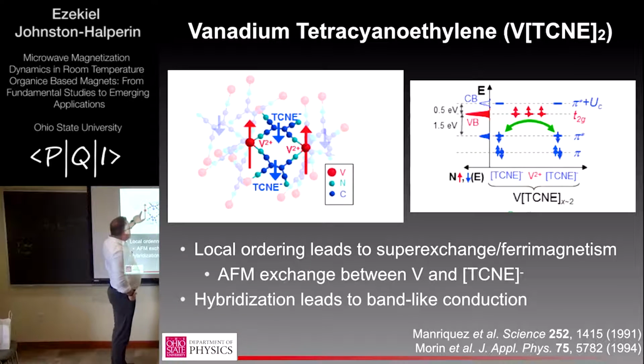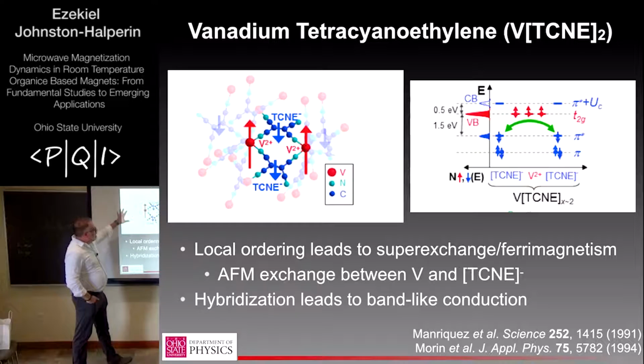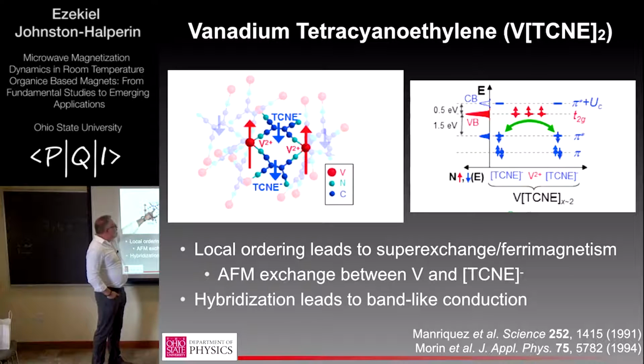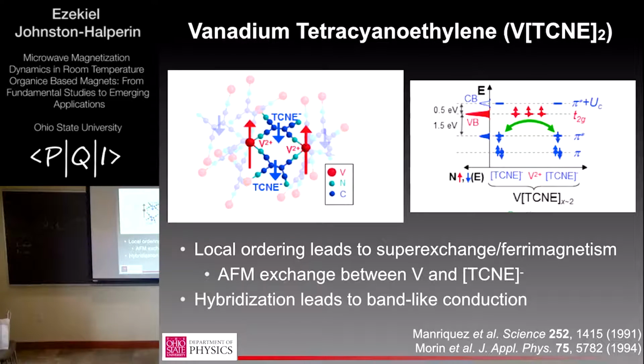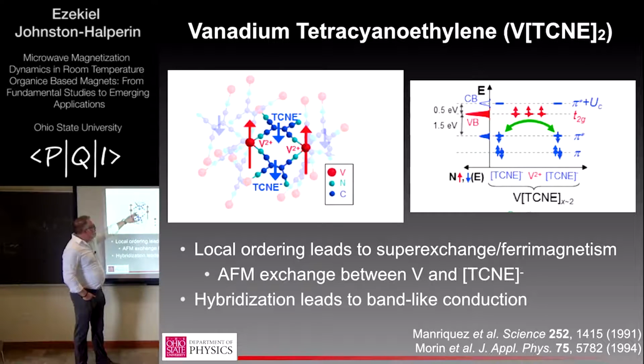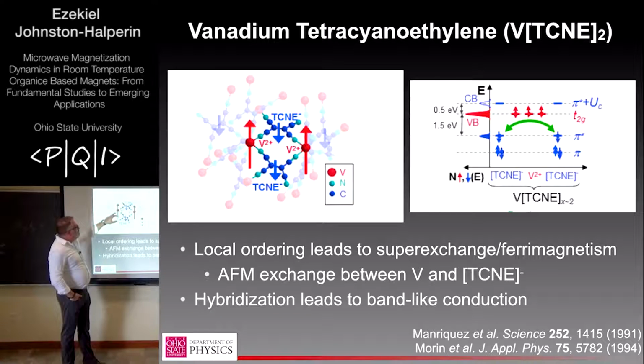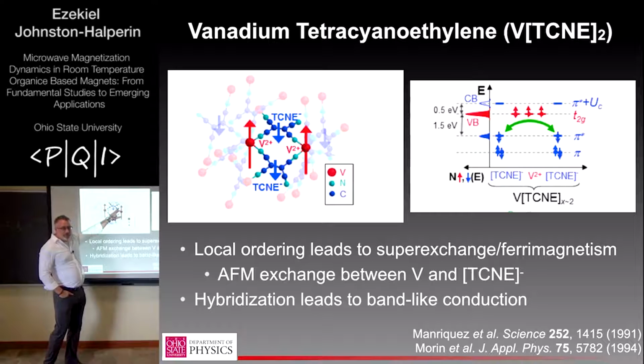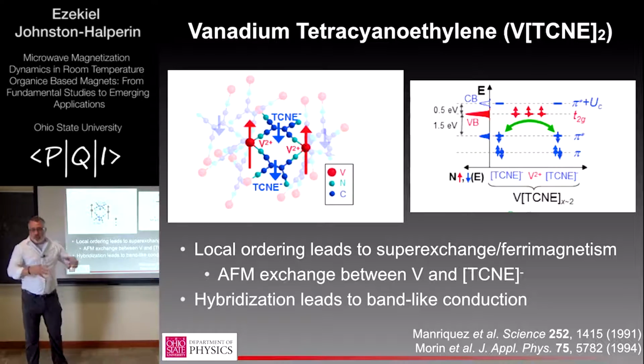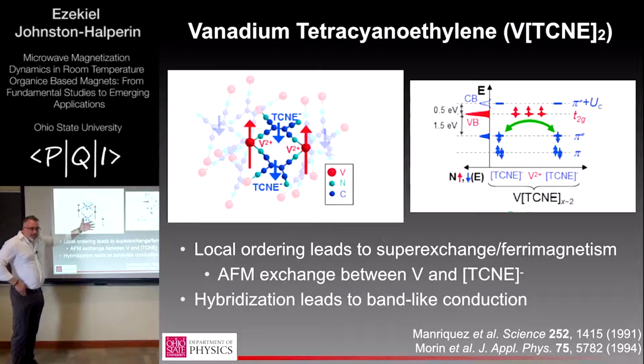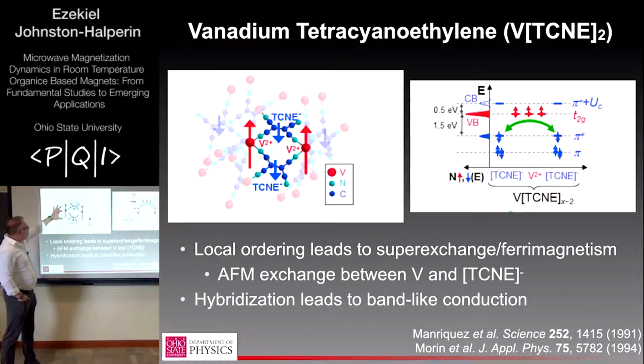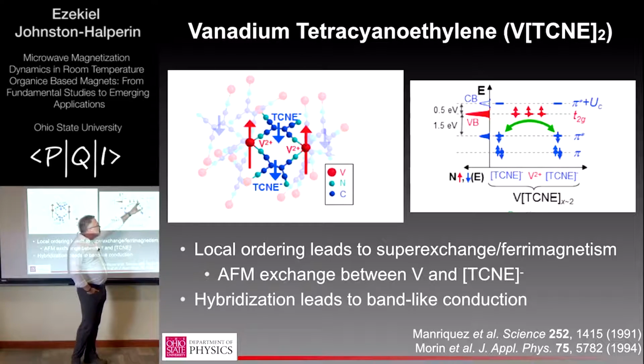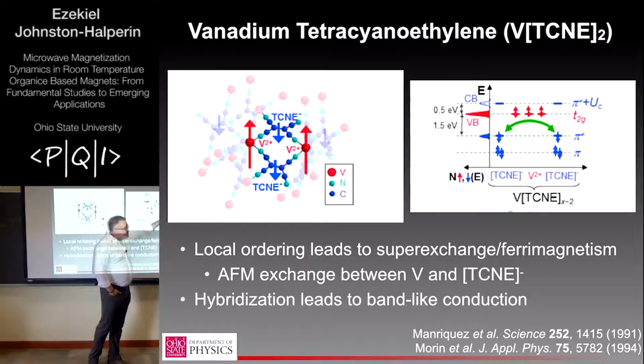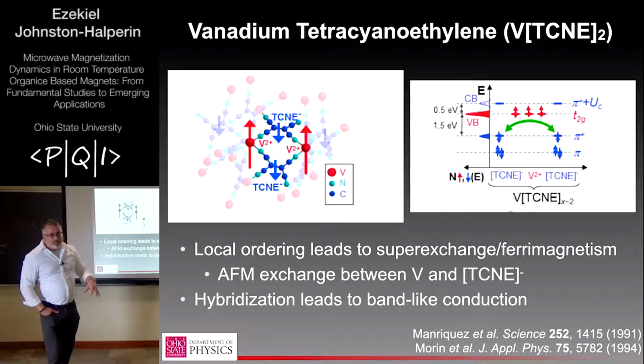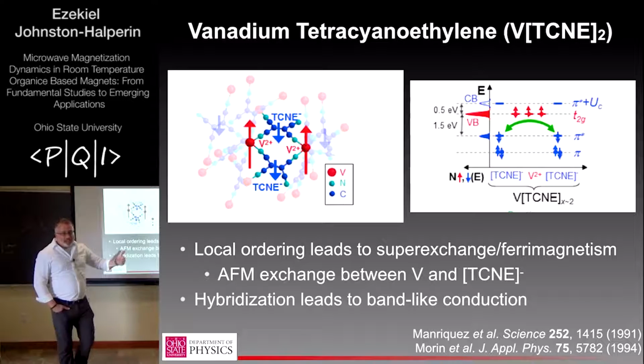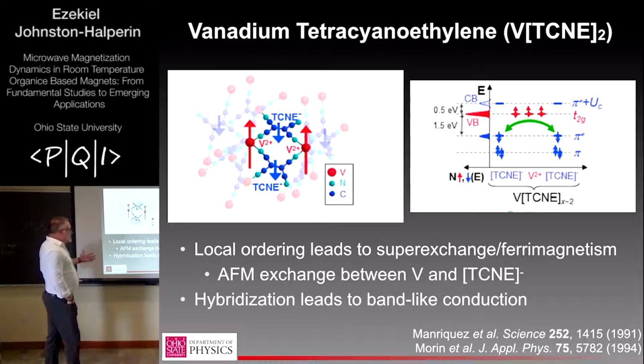In addition to making an electrical connection here as an organic semiconductor, allowing hopping transport throughout the material, you also have an exchange interaction whereby the vanadium, which starts off with five electrons, donates two charges to the neighboring TCNE, giving it a negative charge and an excess moment. So you end up with antiferromagnetic ordering locally between a TCNE and a vanadium, or ferrimagnetic ordering globally. This is an imperfectly compensated antiferromagnet, so you have some remnant moment. You can just do it by counting. You have three electrons on the vanadium pointing one direction. The two electrons that get kicked off into the pi star orbitals of the TCNE point in the opposite direction, so you're left with one net Bohr magneton per formula unit of magnetization.